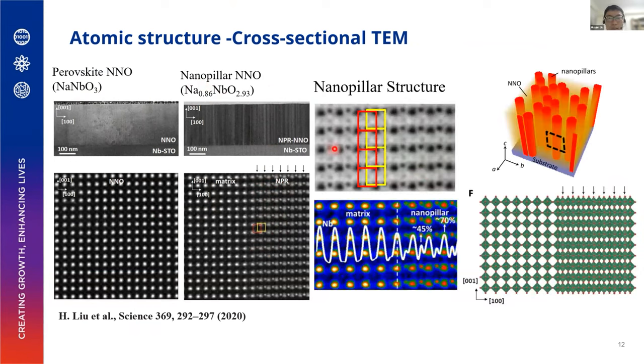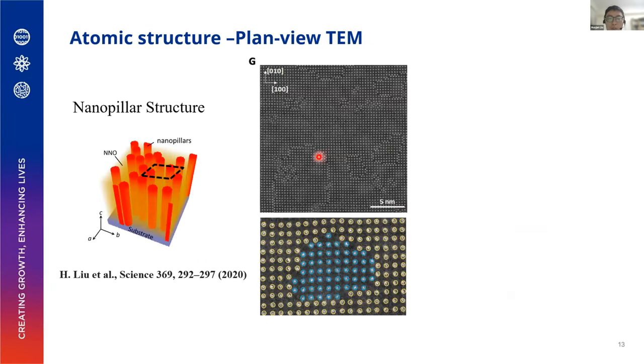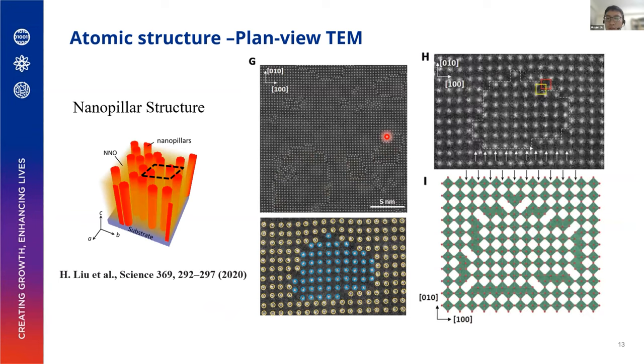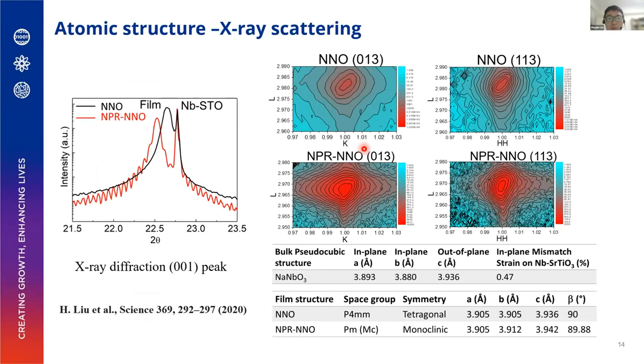Based on our understanding, this is because the nanopillar structure is distributed in this matrix. The extra column of atoms seen is because of the nanopillars overlapping when viewed from certain angles. From plan view, you can see there are pillars of different sizes, which also agrees with our cross-section view of the shifting of the lattices. Okay, we also did X-ray diffraction. The film without nanopillars has a tetragonal structure, but with the nanopillar structures, there is more distortion that lowers the symmetry into a monoclinic structure.